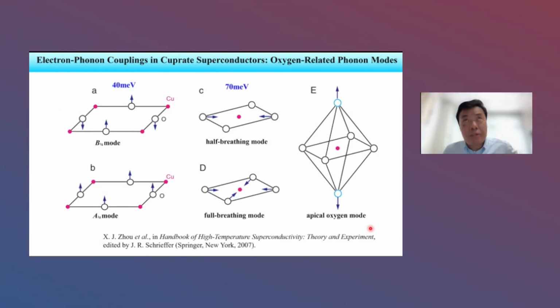So from the previous observations, it becomes clear that these 40 meV and 70 meV mode couplings are really due to electron-phonon coupling, because even in heavily overdoped samples, we can still see these two modes. And in high-Tc cuprate superconductors, usually these modes are associated with the oxygen phonon modes. We have the so-called B1g buckling mode, at an energy of about 40 meV. We have the A1g mode, the breathing mode, half breathing mode and full breathing mode. This is about 70 meV. I think there are two phonons. One is the B1g buckling mode. The other is the breathing mode. So those are the two phonon modes we have observed.